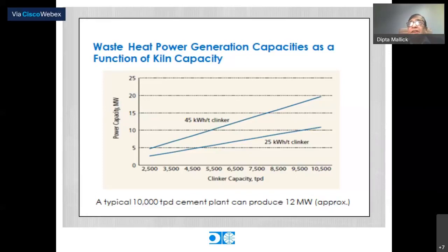Obviously, as I discussed, one major factor is the moisture content in limestone. But generally, a rough thumb rule is, say, 25 kilowatt hour per ton of clinker to 45 kilowatt hour per ton of clinker. This is the range in which electrical energy can be made available with our present technology. Very roughly, as a thumb rule, per 1,000 tons per day you can get a power plant of 1 megawatt. If you have 10,000 tons per day capacity, you can get around 10 megawatt or a little higher.